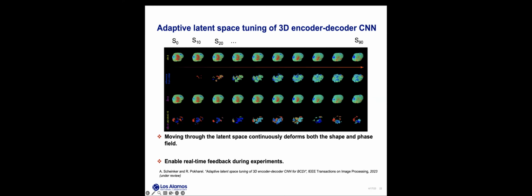So the topmost row here shows the evolution of the tracked object and its phase field going from state 0 all the way to state 90. And the second row from the top here shows the voxels that have changed in density and phase value at these subsequent states relative to this initial state. And clearly you can see that the object has changed a large amount by the final state, where the difference between the voxels is itself an object almost the same size as the original object.